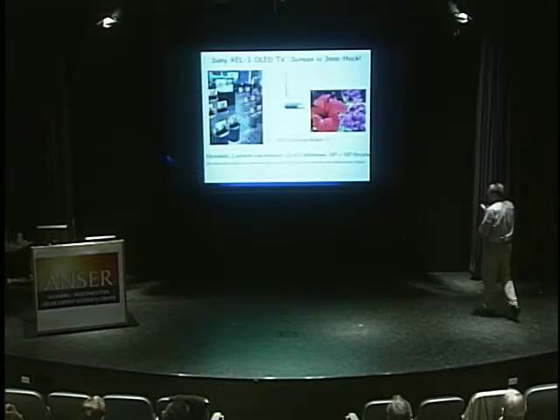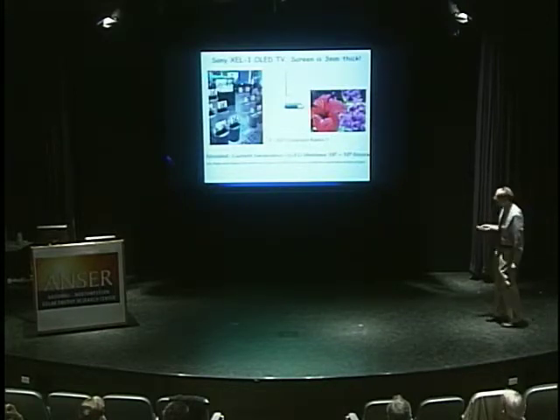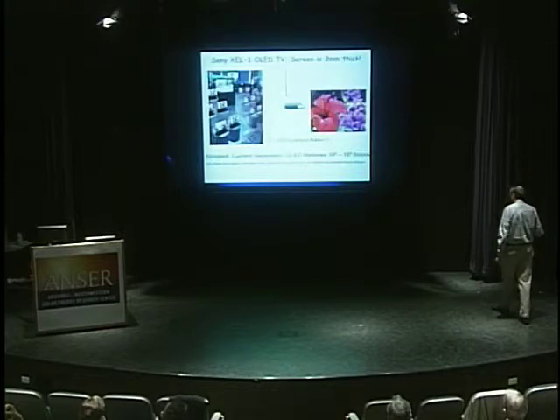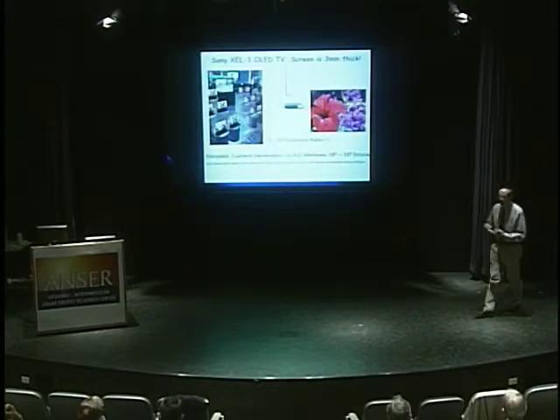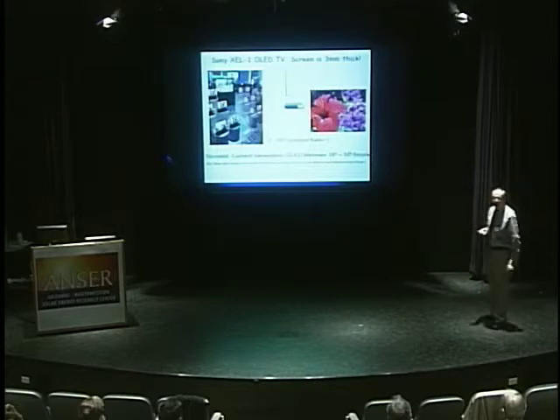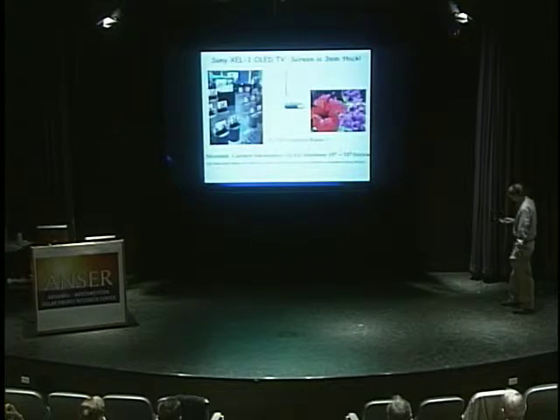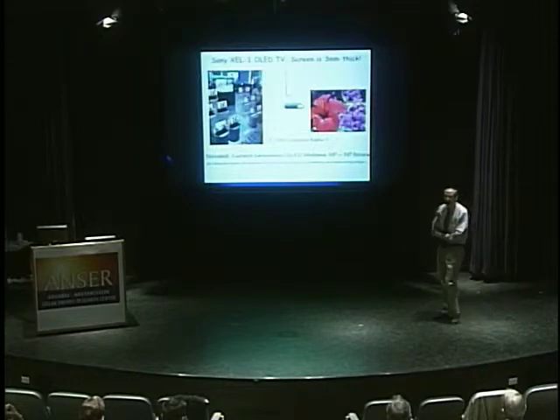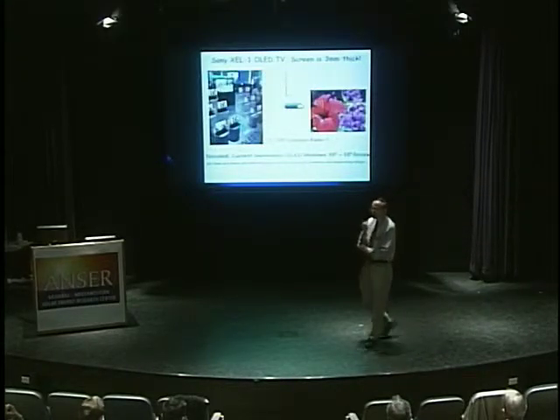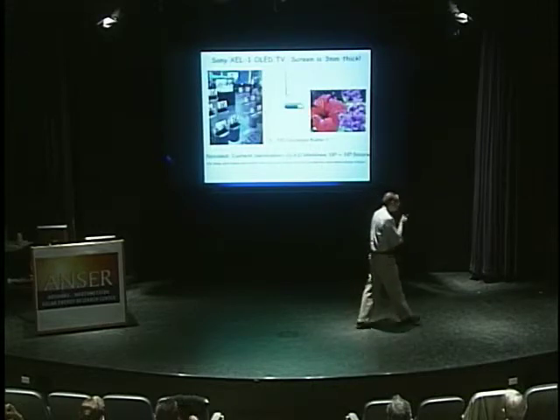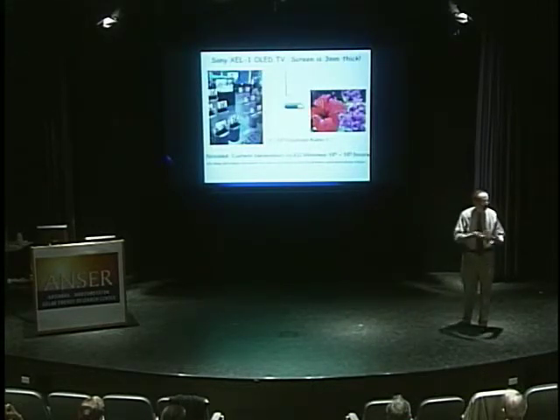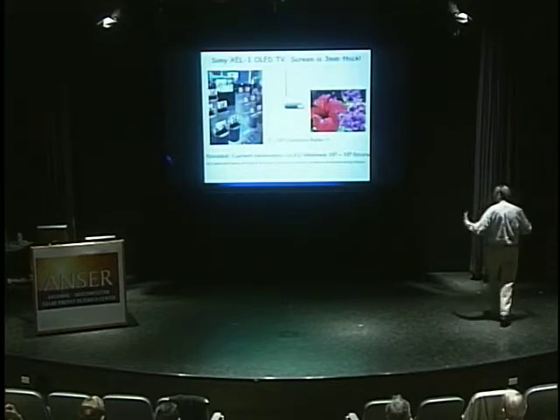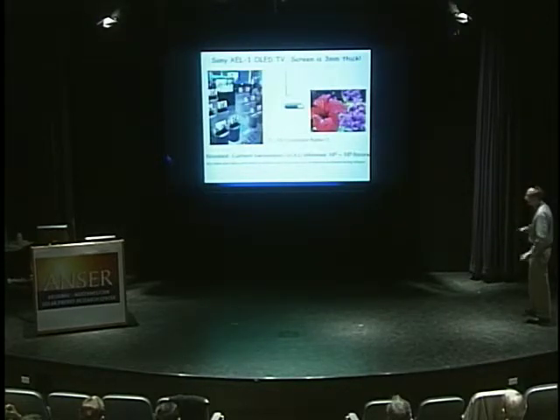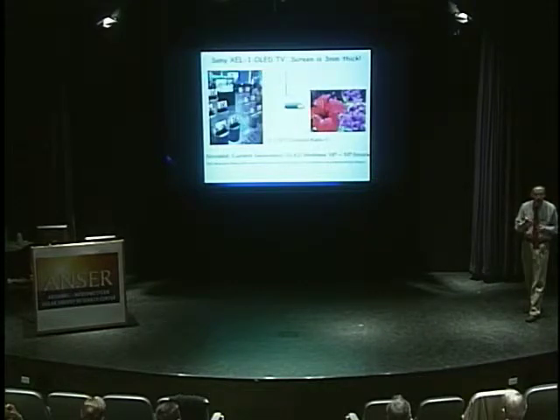And then you say, well, yeah, but they probably only last a couple hours, right? If you go to Novaled's website, the latest kinds of numbers, and these are simulated because you obviously can't do an experiment for 10 to the 6th hours. It's a very long time. But you do accelerated testing, and they're producing OLEDs which have estimated lifetimes on the order of 1 million hours. So the idea that organics are necessarily fragile, they poop out, they die, is not true. It depends simply on the molecule, how it's prepared, and how it's processed and put into the device. So there's nothing intrinsically wrong with organics to do optoelectronics.